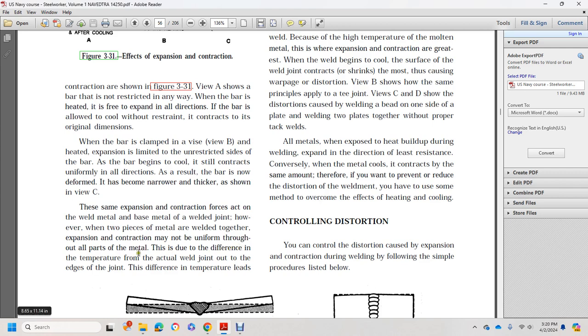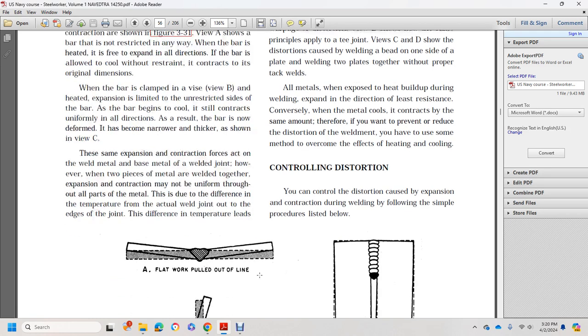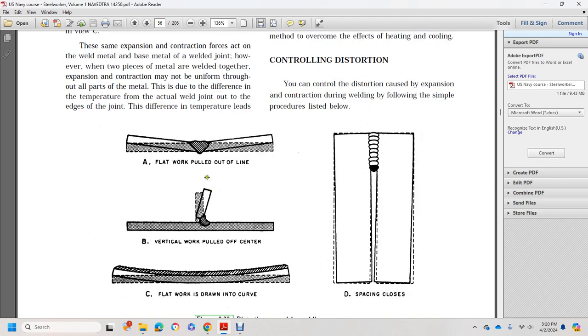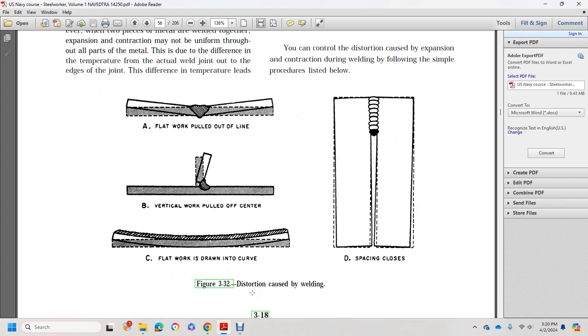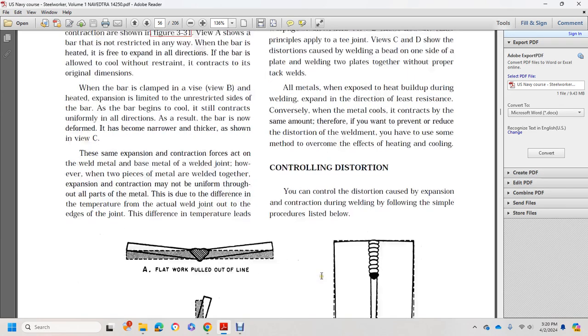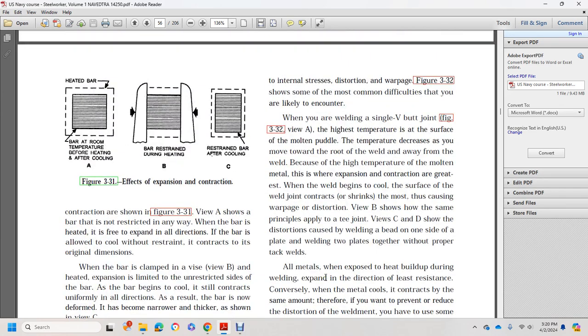This is due to the difference of the temperature of the actual welding joint and the edge of the joint. So you have a flat piece of work pulled out of line, vertical work pulled off center, flat work drawn to a curve, and those distortions can be caused by welding. Internal distortion warpage, shown in Figure 3-32, shows the most common difficulty you are likely to encounter.